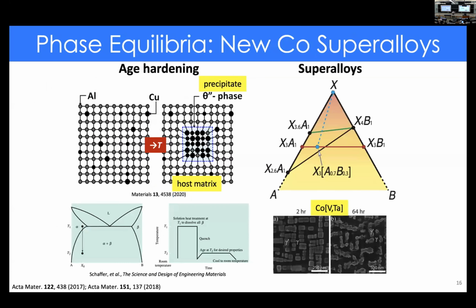We used that concept to find new superalloys. One of the very important mechanisms for making a material very hard is called age hardening. Through a series of quenching and annealing, basically temperature treatments, we can go from something that has this structure, this host matrix, where it's basically aluminum, and we have some dopants of copper, to a new type of structure where we form these precipitates. You can think of them as little nuggets inside of the material. This is really another phase inside, and it prevents the movement of dislocations and makes the material harder.